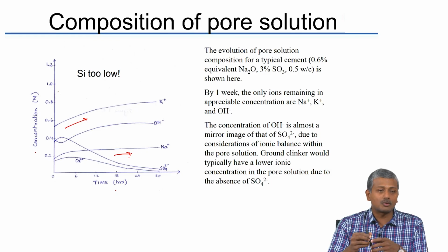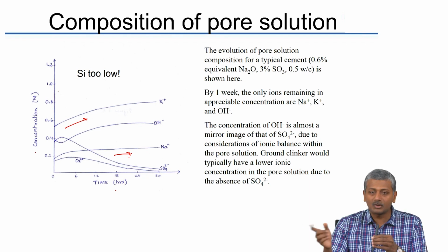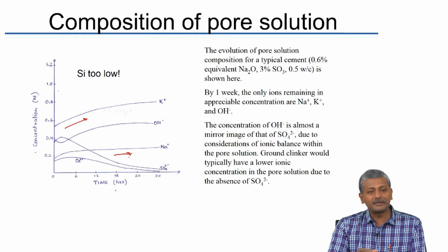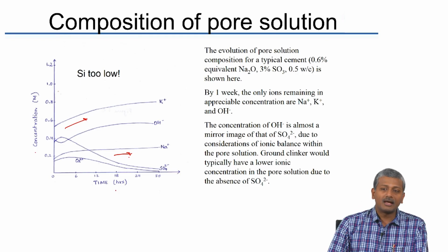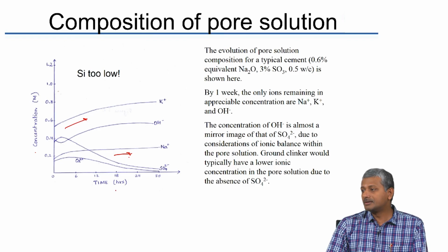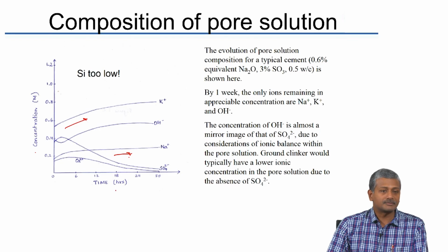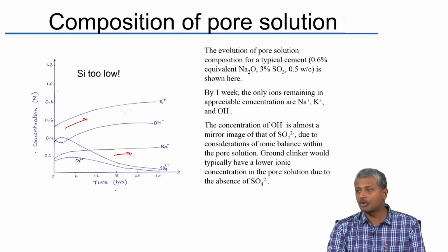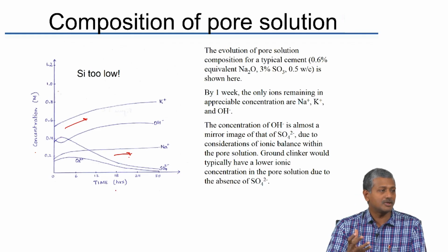So there are very few labs around the world which are actually engaged in determination of pore solution. Now we are trying to create this facility here also. The pore solution is very important to understand, because you will see later that the composition of this pore solution has a role to play in other durability related activities also. For example, in corrosion, there is a lot that depends on how your pore solution is. And alkali silica reaction is another thing, because again the alkalis for alkali silica reaction are getting contributed from the cement. So the pore solution having high alkali means you have a higher susceptibility for alkali silica reaction.